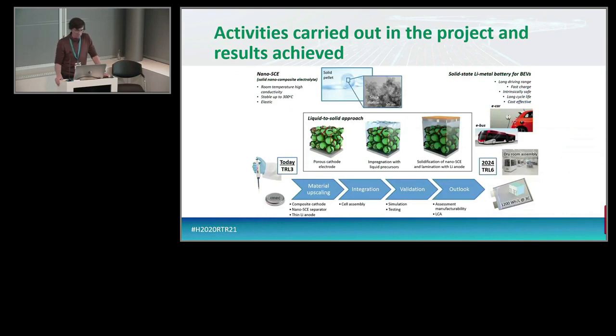Here I try to make it a bit more visual, so to say. You see here on the left side, we start with where we were at the beginning of the project, which was at TRL 3 level with an IMEC technology. And you can see here in the middle, we make this liquid to solid approach more visual. So we want to start from a standard porous cathode electrode. Then we impregnate it with the liquid precursors of our solid electrolyte. And after a solidification step, it becomes solid and we can combine it with our lithium metal anode.